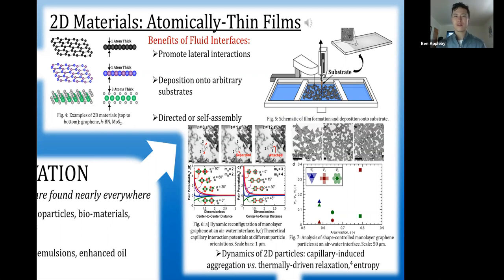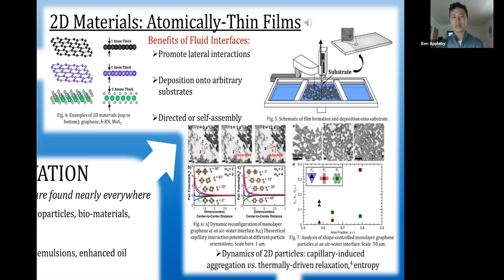In parts A through C, we are looking at 25 micron triangles, 50 micron disks, and 25 micron squares. In part D, we plot the global bond orientational order parameter on the y-axis as a function of area fraction on the x-axis. This bond orientational order parameter is a measure of the extent of total order within the image, where a value of 1 implies all particles are perfectly aligned and a value of 0 implies they are completely randomly oriented. In part C, the squares are packed together very nicely and a value for four-fold order is significant. The main purpose was to compare results with previous simulation studies. The results suggest that particle shape does influence structure due to increased rotational and translational entropy when all particles are optimally aligned.